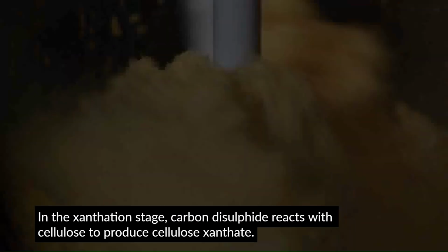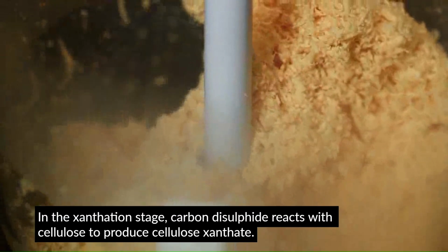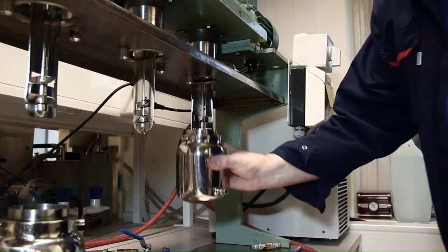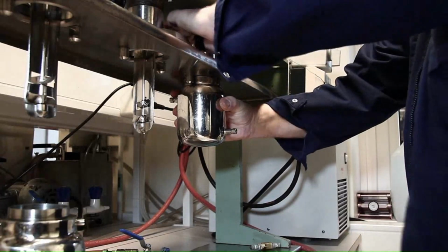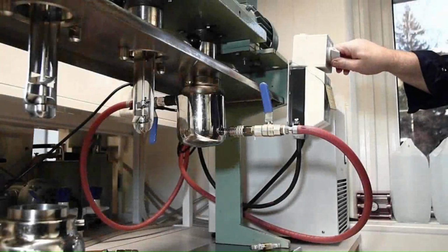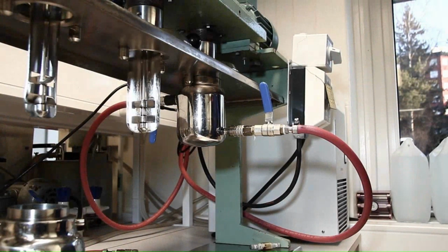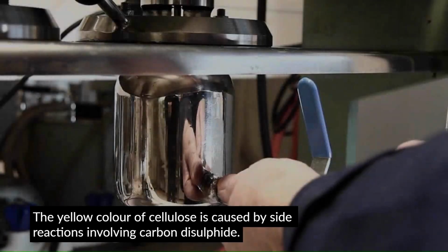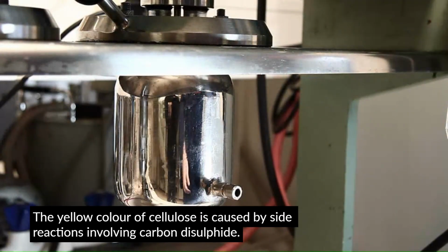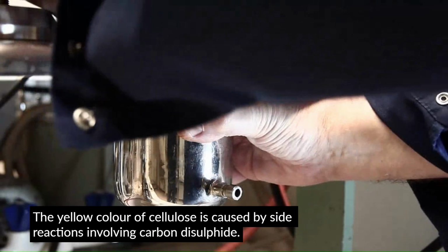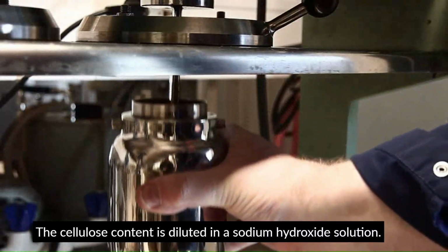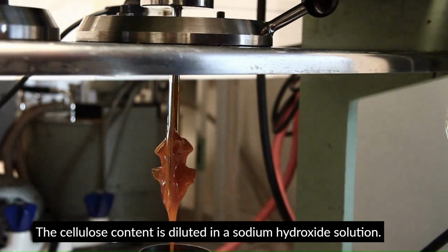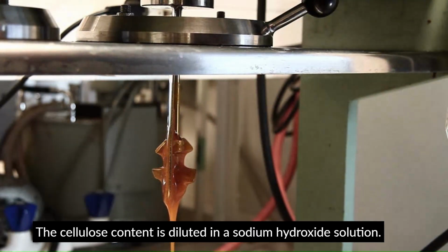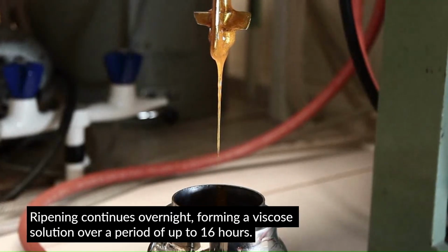In the xanthation stage, carbon disulfide reacts with cellulose to produce cellulose xanthate. The yellow color of cellulose is caused by side reactions involving carbon disulfide. The cellulose content is diluted in a sodium hydroxide solution. Ripening continues overnight, forming a viscose solution over a period of up to 16 hours.